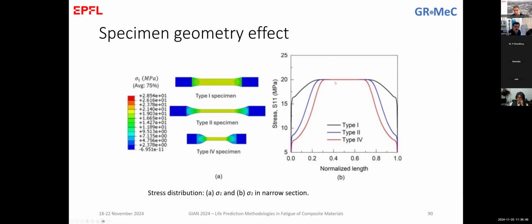We did also a bit of analysis to show why this happens, and probably it is because of the stress at the end. We've seen that at the region of the failure, the stress for all of them is always the same, and it is always in a consistent area where we have a good uniform stress distribution. So there is no problem with any of the specimens in this sense.